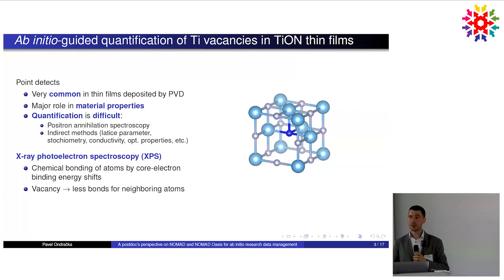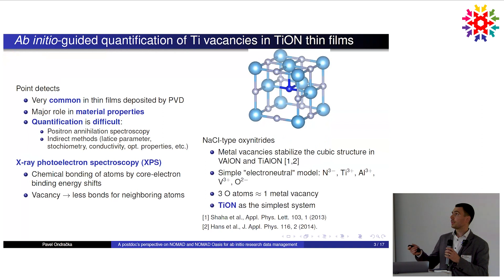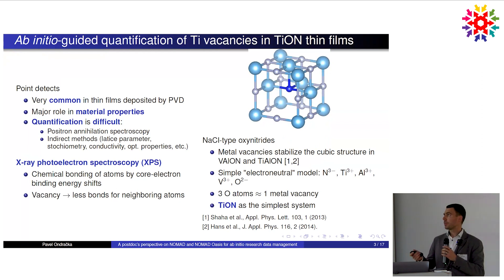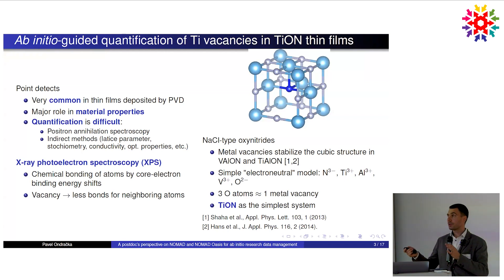If you think about titanium nitride and mark a nitrogen atom, and then start introducing vacancies by removing titanium atoms, this is a big change of the local environment. One of the material classes we were working with is the sodium chloride type oxynitrides, which are sometimes better than nitrides because they have better high-temperature stability and inherently have a lot of vacancies. That's because when you replace nitrogen, which is usually 3−, with oxygen, which is 2−, you need metal vacancies to stabilize the structure. So in a simple approximation, for every three oxygen atoms in your structure, you have roughly one metal vacancy.